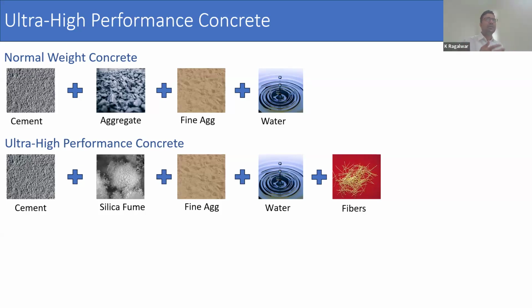And that's how they came across that eradicating large aggregates and focusing on smaller aggregates will lead to higher strength. With that also came the advent of using supplementary cementitious materials such as silica fume. Supplementary cementitious materials such as silica fume basically worked on the hydration products. So the byproducts of hydration further react with silica fume and form supplementary hydration products which give higher strength, which is known as CSH, which we'll see in the next slide. So that CSH, along with the smaller aggregates, does two purposes. It increases the strength of the paste, and it also reduces the flaw, which means a reduction in flaw, so higher stress is required to initiate a crack or failure in the concrete.